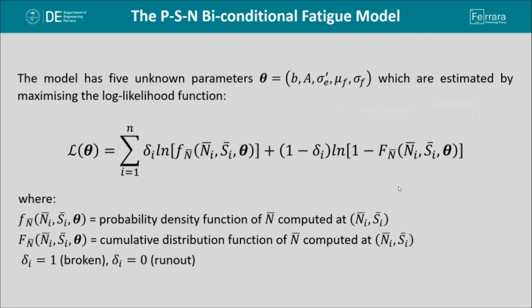The first parameter, B, is related to the slope of the S-N curve in the finite life region. The parameter A is related to the Basquin's law for the finite life region. And finally, the last 3 parameters are respectively the scatter parameter for the logarithm of the cycles to failure at a given stress amplitude, the logarithm of the fatigue limit, and finally the scatter parameter for the fatigue limit itself. The model also takes into account both the broken fatigue specimens and the specimens that ran out.